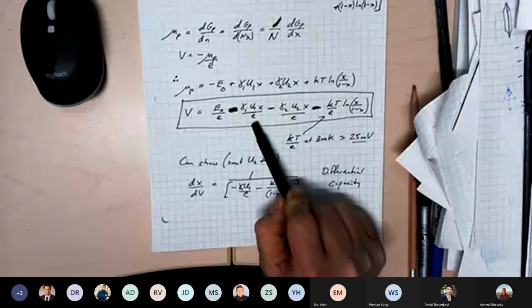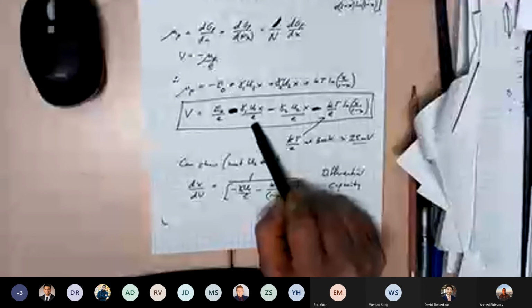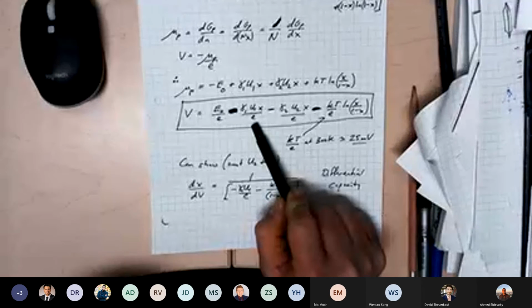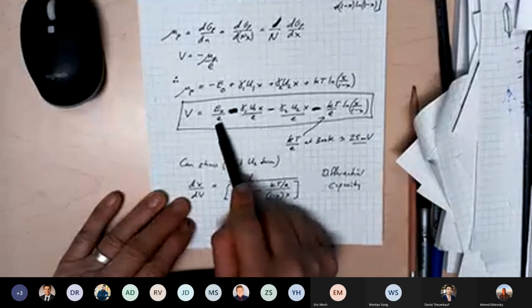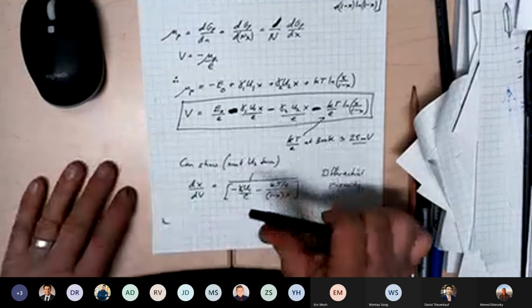The lithium atoms are 8 angstroms apart in Mo6Se8. They're so far apart and they're in a metal, they hardly feel each other. In titanium sulfide, they're super close and they're not well screened. So the point is that from one material to the next, these parameters change. E0 and the U's change from material to material.